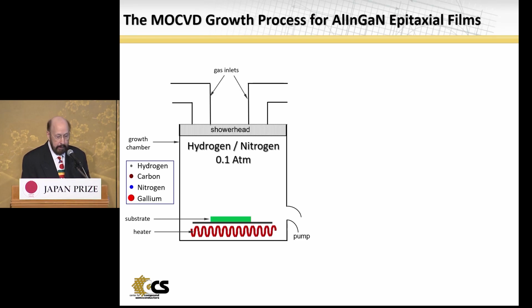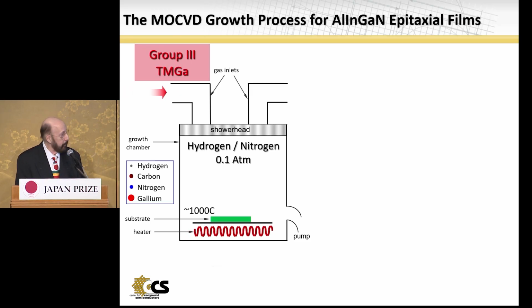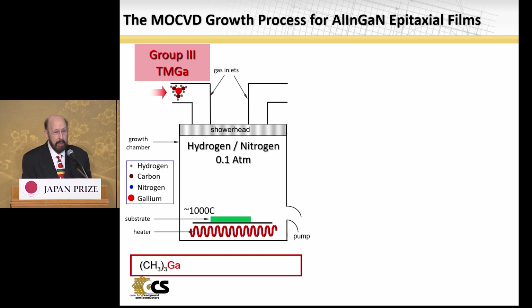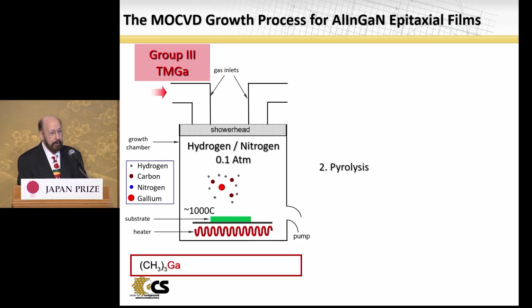We begin with a heated susceptor upon which a substrate is placed, and then we inject our precursors after heating to 1,000 degrees or so. In this case, trimethyl gallium, which is a gallium atom with 3 methyl radicals attached. We inject that vapor into the reactor. It diffuses to the growth surface and pyrolyzes in the high temperature region above the substrate.